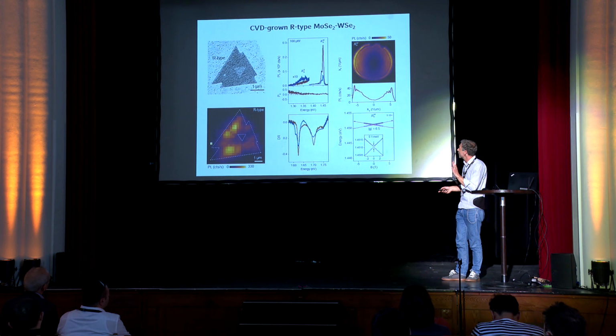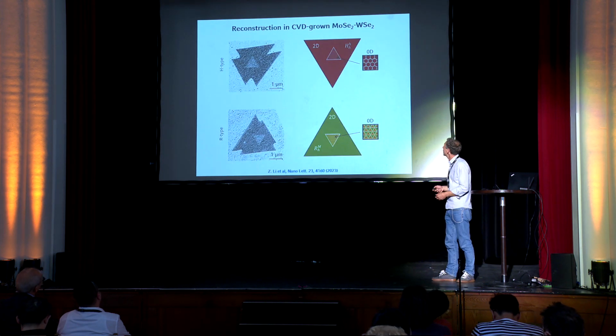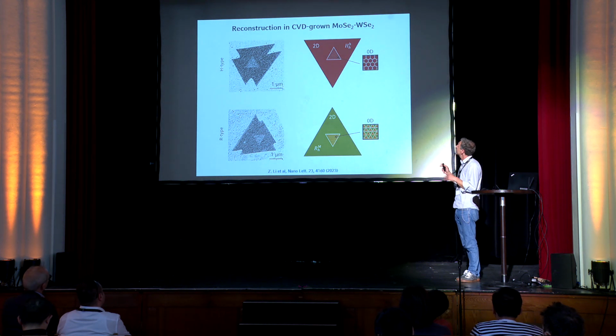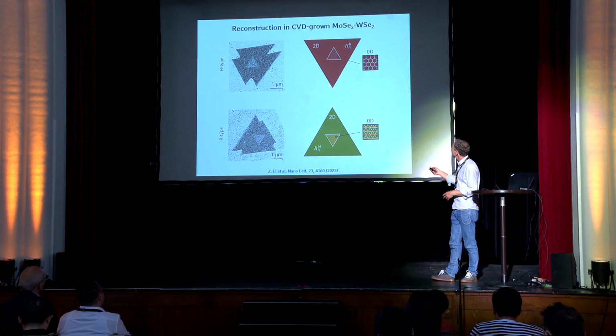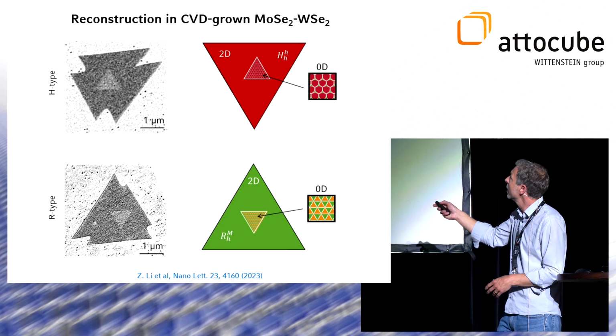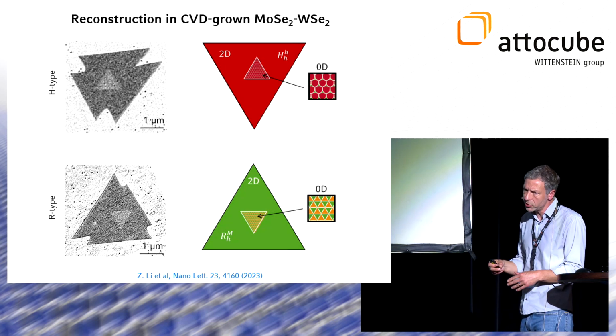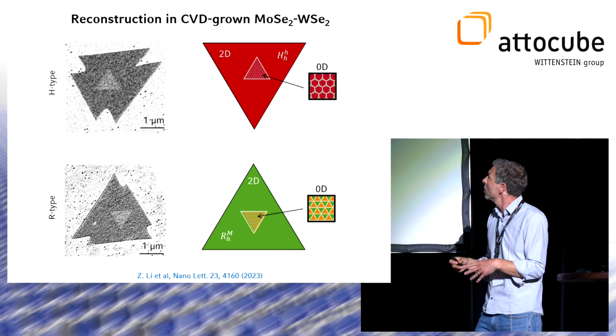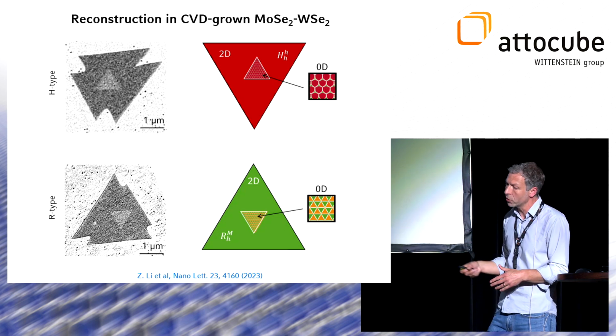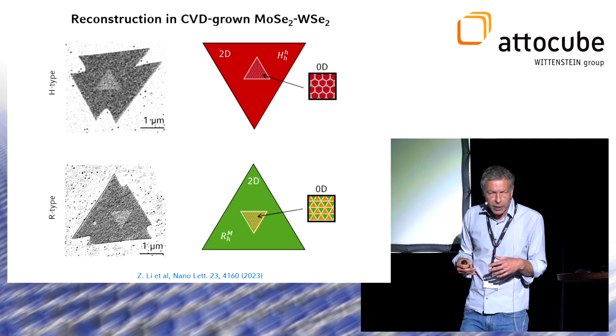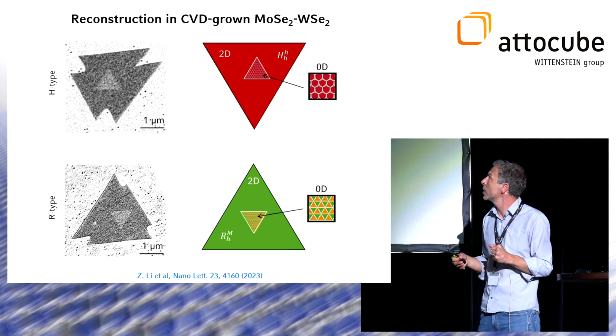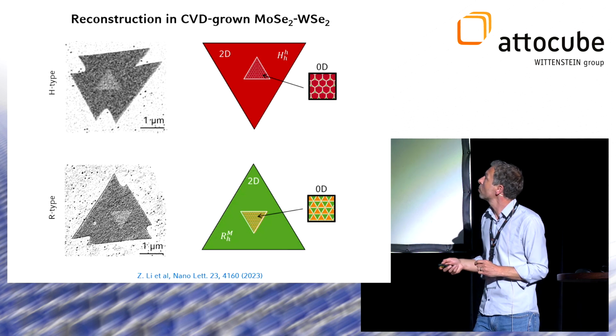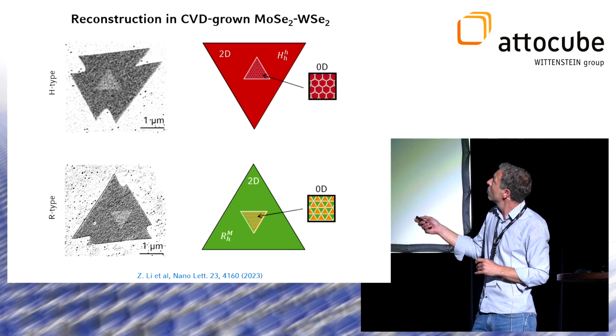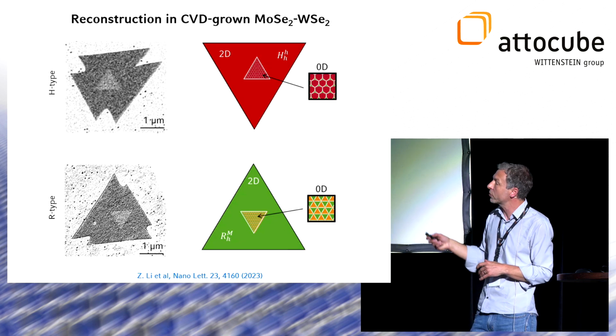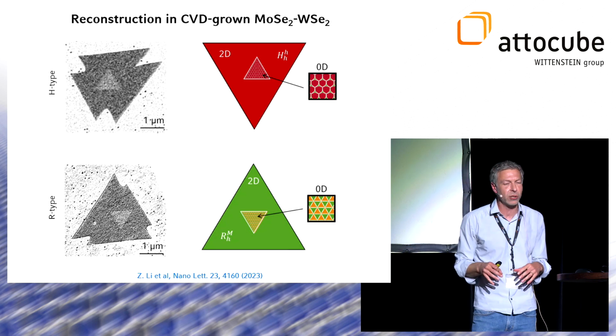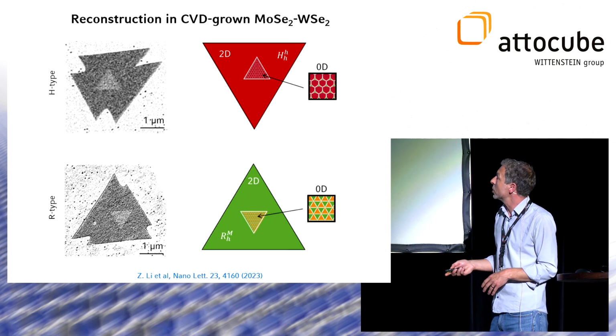Yes, so a lot of insightful spectroscopy. Let me skip this for the sake of time and share with you our conclusion. We believe that the inner core of the triangle is nothing else but a periodically reconstructed little triangle, whereas the periphery, and this is something that we confirm optically, but also in high resolution transmission electron microscopy done by our friends in the group of Knut Müller-Kaspari at LMU, is one exclusive atomic registry. So we again have large-scale reconstruction, both in H and R type.